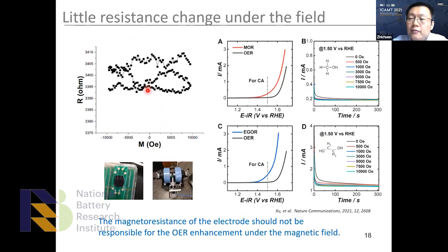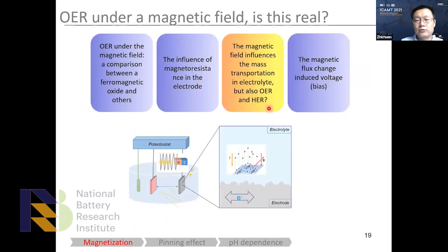And then we actually measured the resistance change under the field. We found that there is no big difference. And also we measured other reactions which do not involve spin-selected electron transfer. We can observe that there is no significant increment under the magnetic field, right? So this says the phenomenon is unique to reactions which involve spin-selected electron transfer.